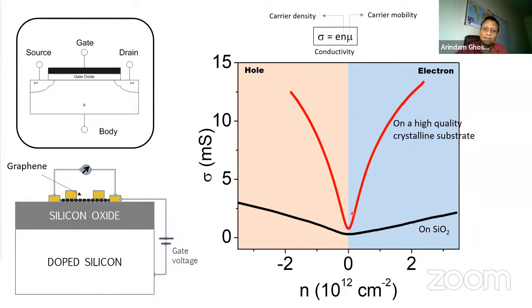Now, it turns out that if you look at the slope of the sigma versus density, you get the calculation estimate of the mobility. So when we do that, the number that comes out, even on silicon oxide, the mobility of charge in graphene is in the order of 1,000 to 10,000 roughly. Whereas if you put it on the single crystal substrates, very nice quality substrates, which have got no impurities, etc., then this number can be much, much larger, up to 1,000,000 centimeters per volt second.